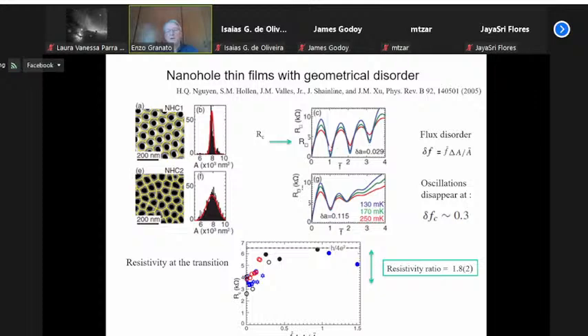First, they find that the oscillations that you see as a function of frustration decrease in amplitude as a function of frustration. And they also find that they disappear above some critical value of frustration in terms of a disorder parameter, which they define as the average frustration times the disorder associated with the area. So there's an effective flux disorder in the system, which is the product of the average frustration times the disorder in the areas. They find that the oscillations disappear roughly when this parameter is around 0.3.